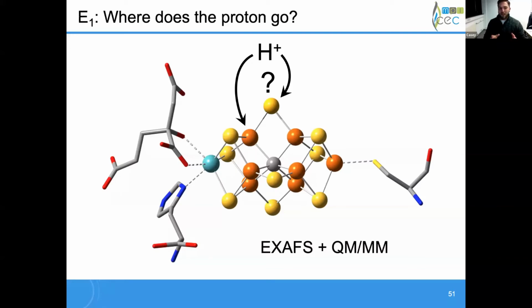And in terms of efficiency, this back reaction of hydrogen production seems to be much higher in vanadium and iron nitrogenase. So vanadium nitrogenase is less electron efficient than molybdenum nitrogenase, and iron nitrogenase is even poorer. Recent studies have shown that the limiting stoichiometry is the same for all 3 enzymes, but they're just not as effective at binding nitrogen before releasing hydrogen. So it does seem like molybdenum is doing something important there. But of course, it's also impacted by the secondary coordination sphere very heavily. Yeah, good. Please continue so we get to the end of your time.